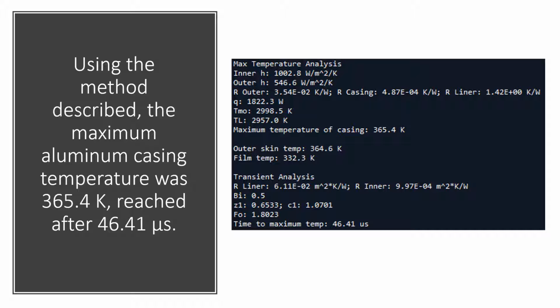Using the method described, the maximum aluminum casing temperature was 365.4 Kelvin, about 200 degrees Fahrenheit, reached after 46.41 microseconds, or 4.6 times 10 to the negative 5 seconds. The first section displays the heat transfer coefficients, resistances, heat transfer rate, mean out temperature of the hot flow as TMO, and the temperature of the liner exposed to the hot flow as TL. This temperature, as a note, is likely to ablate the phenolic liner. However, this will not be considered in this project.